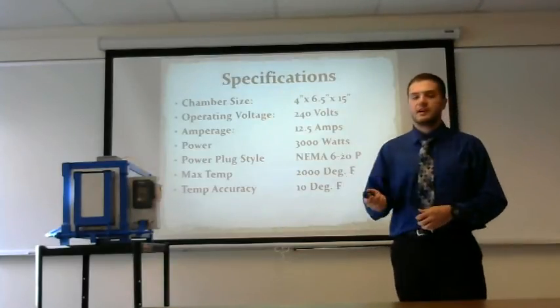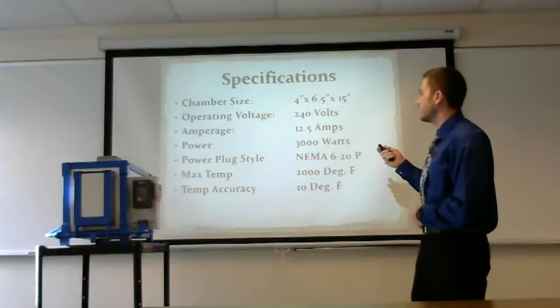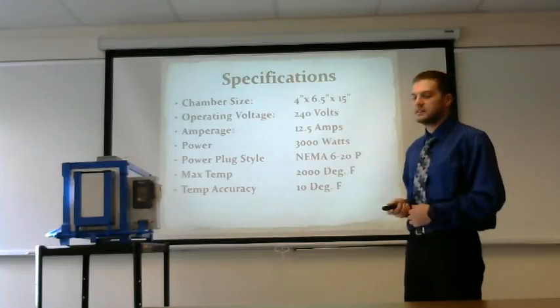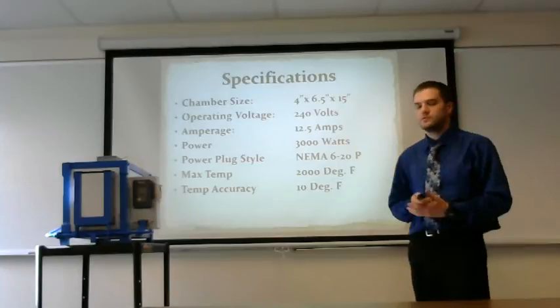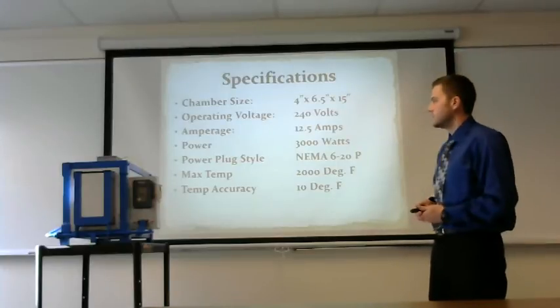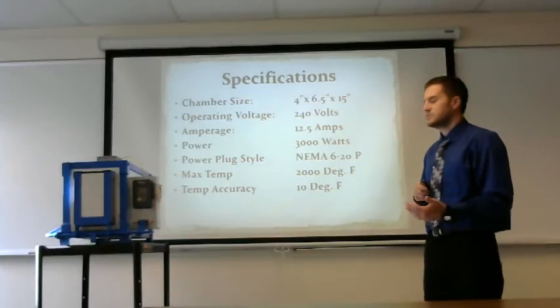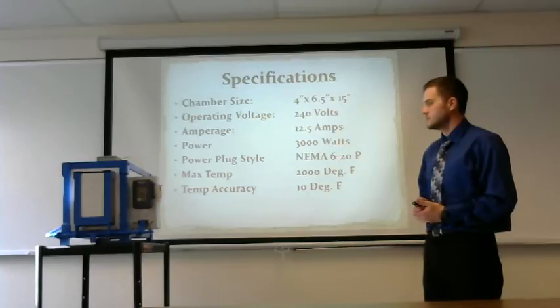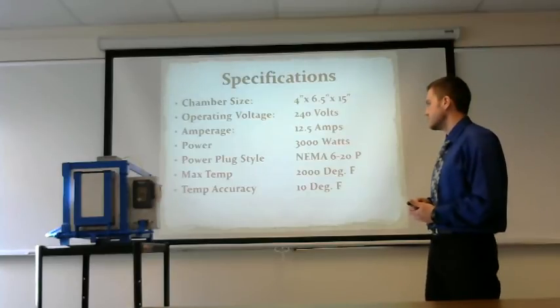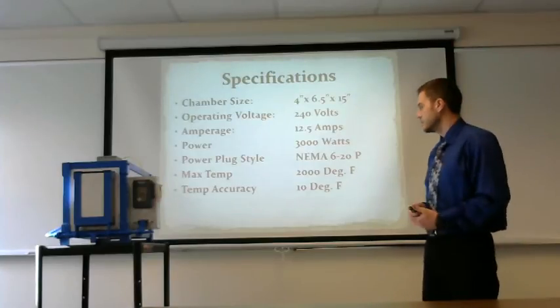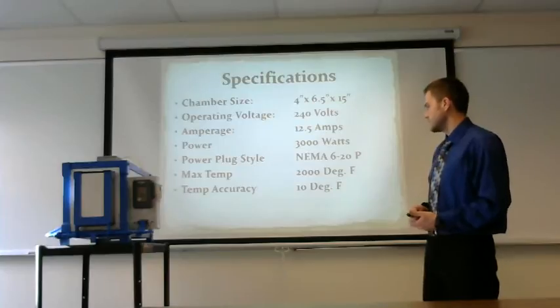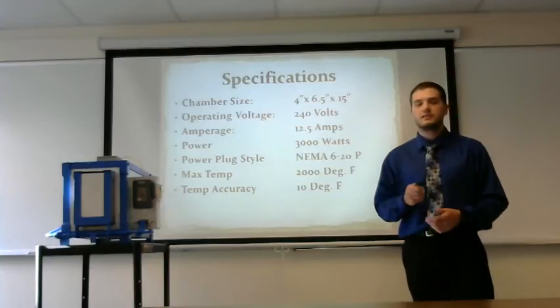The chamber size is 4 by 6.5 by 15, it operates at 240 volts, and it draws 12.5 amps. The elements dissipate 3000 watts, and it uses a standard NEMA 6-20 plug. The maximum temperature is 2,000 degrees Fahrenheit, and the accuracy is guaranteed to within a few degrees Fahrenheit.